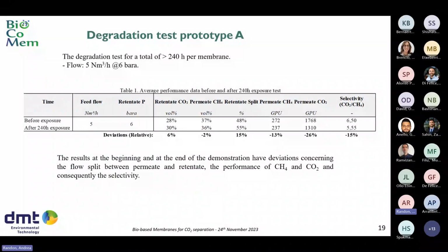And here is how they perform the accelerated tests. They did a degradation test for a total of 240 hours per membrane, with a process condition of 5 normal cubic meters, which was the feed flow rate, at 6 bar. And as you can see, for example, here in the permeances, here is how they assess basically the degradation, and you can see that the permeance of the CO2 is decreased up to 26%.